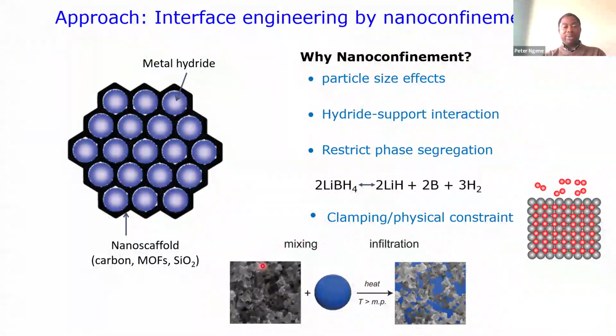Very simple. We just mix. So this is, in this case, carbon, and this is our bulk metal hydride. And then if you just infiltrate, either by heating or doing what we call impregnation, then you will now have all these metal hydrides dissolved, or confined, in the small porosity of the carbon.